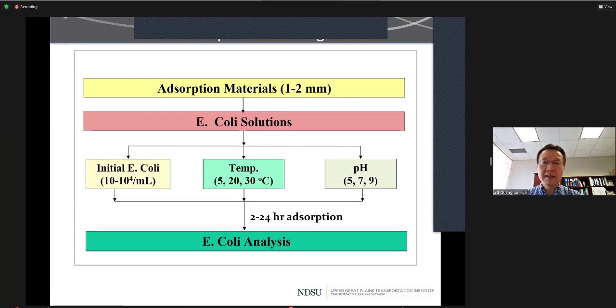And this is the batch study design. First, we select the adsorption material, and we use sieving to collect the material that is in the 1 to 2 millimeter range. And following that, we create simulated E. coli solutions. So basically, we grow the E. coli media in the lab, and then we dilute the E. coli culture into different concentrations from 10 to 10 to the 4 per milliliter. And we conduct a batch adsorption experiment under different temperatures from 5 to 30 degrees Celsius and 3 pH values, 5, 7, 9, to cover a wide range of real stormwater conditions.